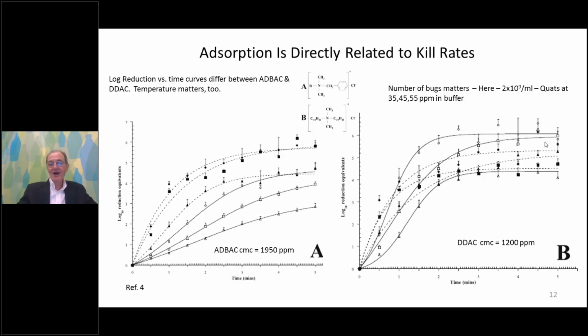Okay, we'll move on. So the answer is when we hit a log R plateau versus time, the kill rate of the bugs is 0. There's no more killing going on. The quenching effect has taken over, and you could wait for days. You're not going to reduce the number of Staph aureus organisms anymore. So that's the point of these biological kill curves that surfactant chemists aren't real familiar with.